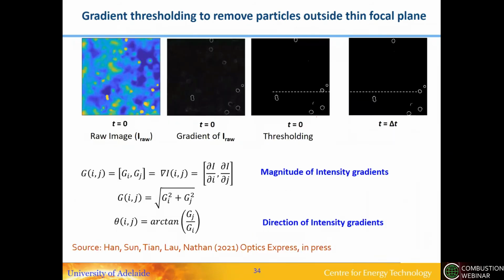So this is an example. This is the gradient detection method. You see the raw image has all these particles, many of which are out of focus, and only a few that are in focus. Once you do the gradient detection, everything except the ones that are in the focal plane disappears. This allows spatial resolution even in very densely laden particle flows. And this is what we've been using to also do measurements.